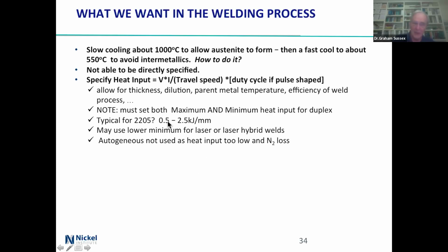Maybe you can get to a lower minimum if you're using a laser or laser hybrid welds, because you're not putting quite so much heat in. But you wouldn't use autogenous because the heat input's going to be too low and because any nitrogen will just go away.